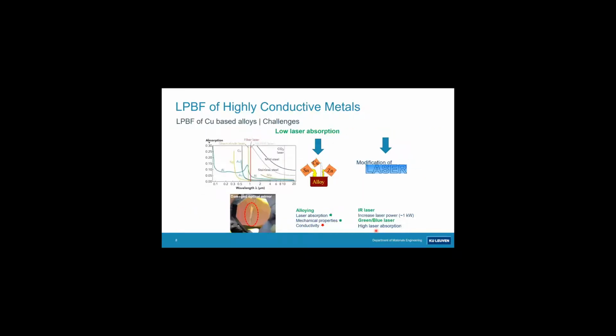Now, the major challenge is that we normally use near-infrared lasers emitting laser light at a wavelength of about 1060 to 1070 nanometer, and you see it here. So this is the fiber laser wavelength which we use. And copper, for example, this curve, has a very low absorption. These are curves for flat plates, very plane parallel, nicely polished. So they have a very low absorption. And how can you mitigate that? You could alloy the copper, of course, especially with elements in solid solution, but as I just mentioned, when you do that, you will compromise on the conductivity.